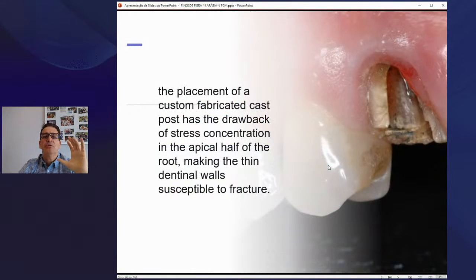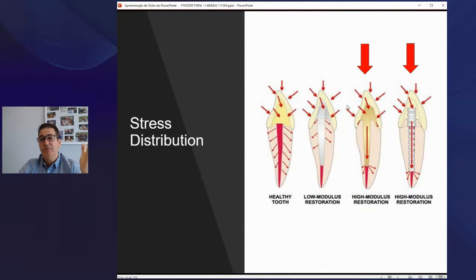The placement of those fabricated cast posts also has the drawback of stress concentration at the apical half of the root, making the thin dentinal walls very susceptible to fracture. And I bet you guys have been seeing this. Fractures like this, especially in premolars, are caused by fracture at the thin walls of the tooth. But this is because of stress distribution, and that explains a lot of things.